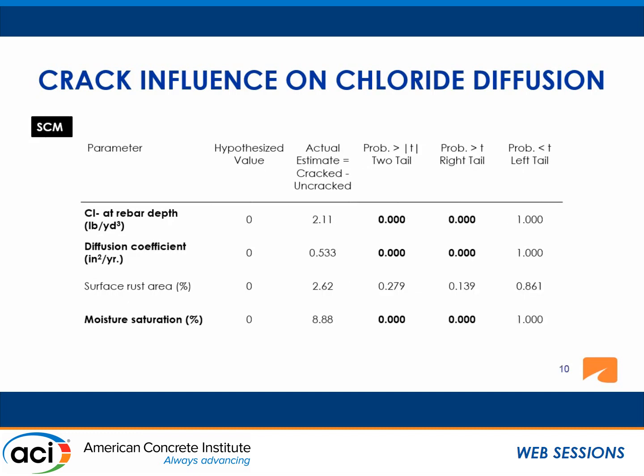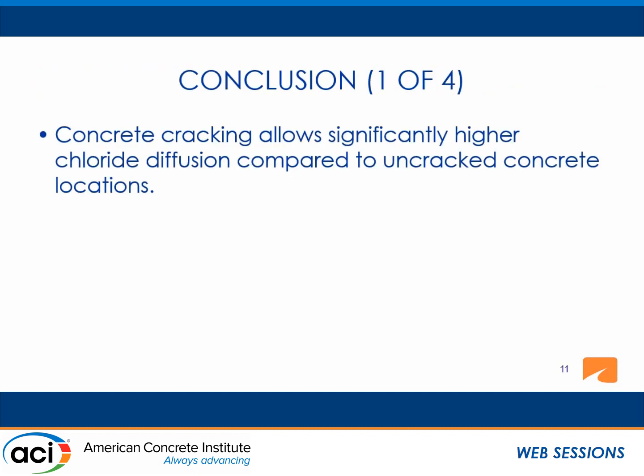And these are the results for the exact same analysis for the decks with SCM. And we found exactly the same results, like the chloride at rebar depth, the diffusion and moisture seem to be significantly higher at the cracked locations. So this is the first conclusion.